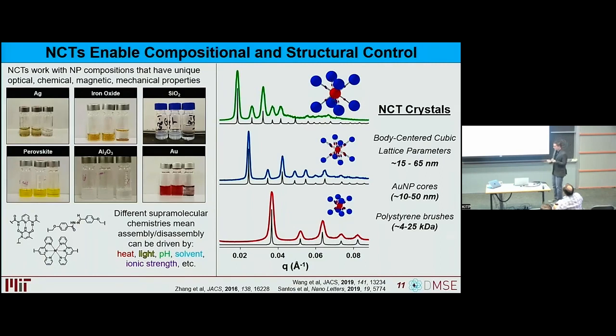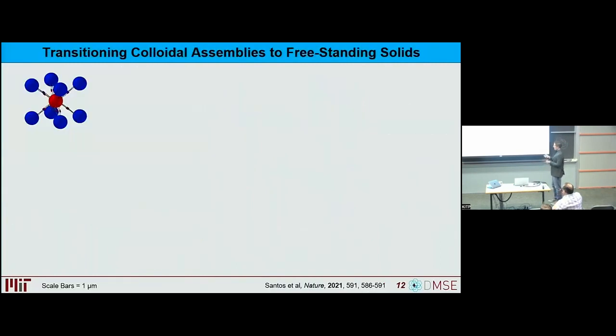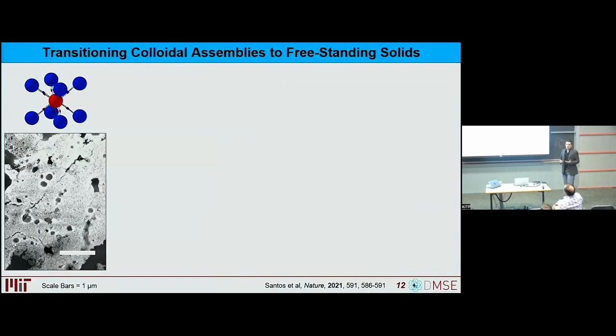The challenge is if we take this lattice, which if you can see right here, I've omitted a lot of the polymers just for the sake of clarity, but there's a lot of empty space in between the particles. And so if I evaporate out the solvent, we lose a lot of our ordering. Capillary forces basically pull everything apart. And if you look closely in this SEM, you might see some regions where the ordering is retained, but by and large, it's just a mess.